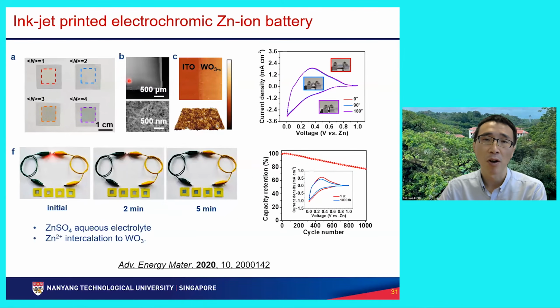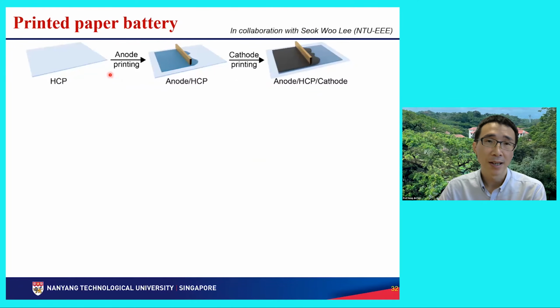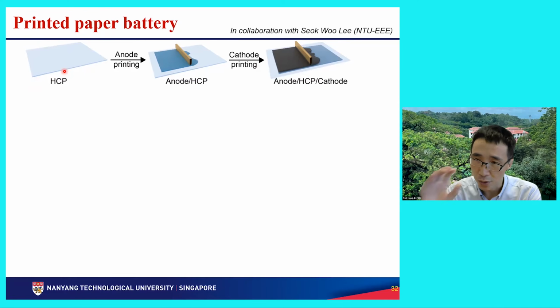Not only inkjet printing, we can also print the battery on paper. Let's say you choose a paper. This paper can be normal printing paper, or filter paper, but the paper is engineered with a hydrogel. So this is a hydrogel-coated paper. Paper is made of fibers. If you zoom into the paper, you see these fiber structures, and between the fibers there are a lot of micropores. The micropores are embedded with the hydrogel, so the paper becomes stronger and more robust.